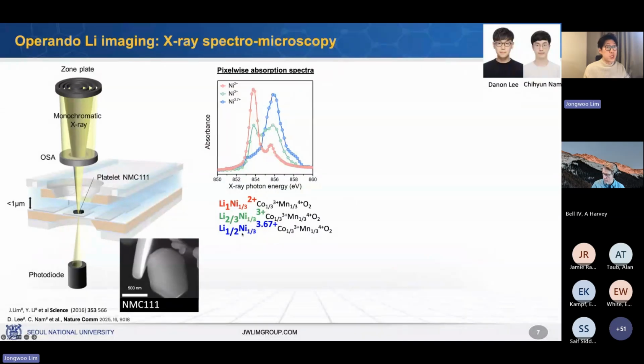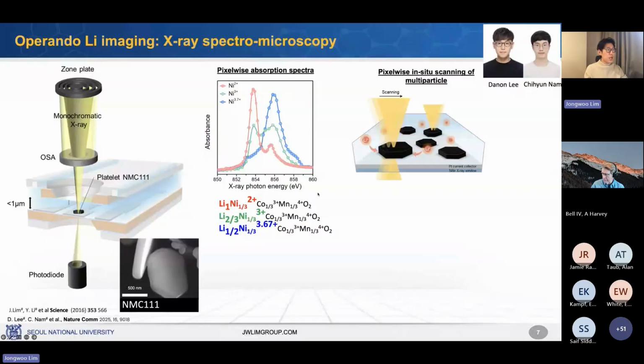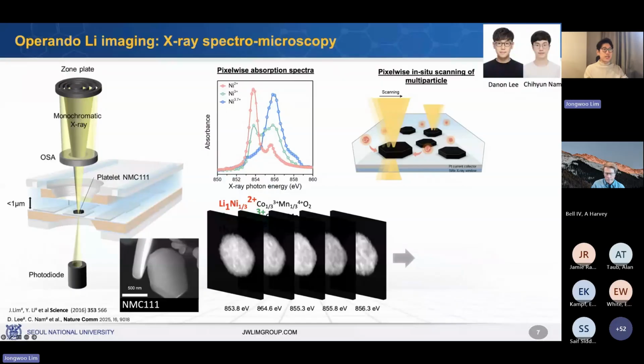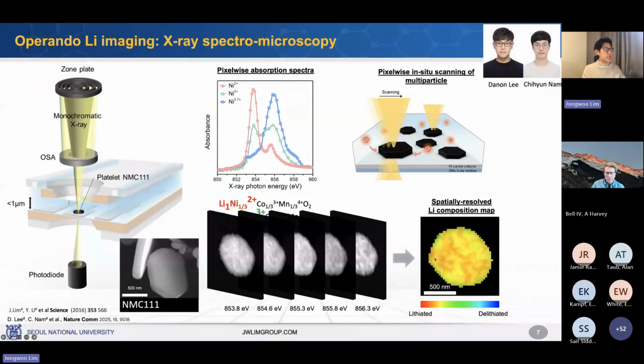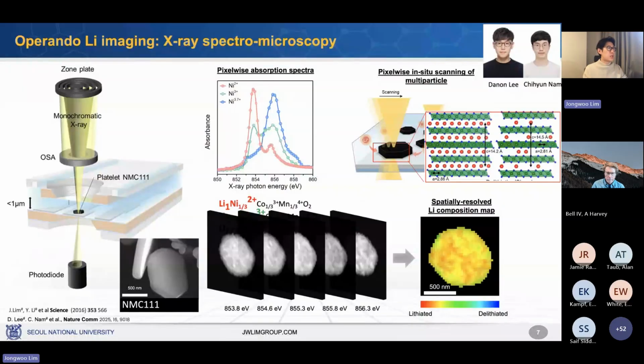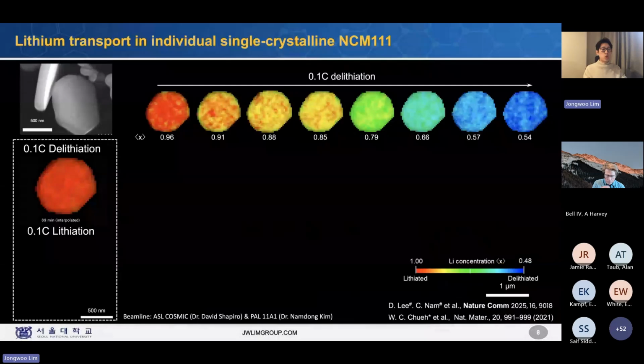And then we raster scan the particle with the focused beam, and we collect all the data points at the individual energy points. And at the end of the day, what we get is the lithium concentration map. One of the beautiful things of this technique is that we are sensing the L-edge of the nickel, which means we can measure lithium concentration down to 0.1% fluctuation because it is so sensitive to the oxidation state. So, long story short, we collect the lithium concentration movement in situ.